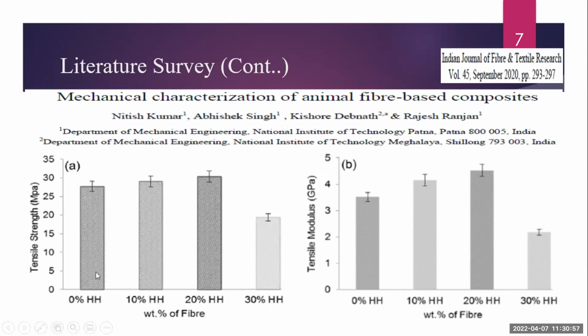From their test results, again we can see similar results to what we have discussed earlier. The first sample was fabricated using 100% polylactic acid. Here 10% of horsehair was mixed into 90% of polylactic acid, 20% of horsehair was mixed with 80% of polylactic acid, and in the same way, 30% of horsehair was mixed with 70% of polylactic acid. Again we can see that 20% of horsehair mixed with 80% of polylactic acid gives the best result compared to the other samples.